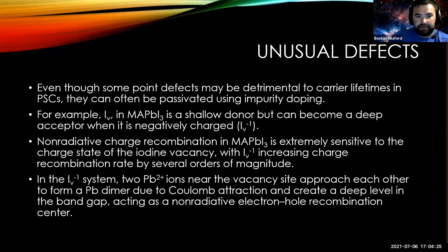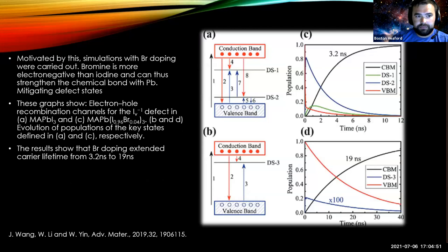But they found that In the Iv-1 system, two lead ions will approach each other and form a bond and create a deep level in the band gap, which again acts as a recombination center for the charge carriers. So knowing that, doping simulations with bromine were carried out. Bromine is more electronegative than iodine and can thus strengthen the chemical bond with the lead, which mitigates the defect states.